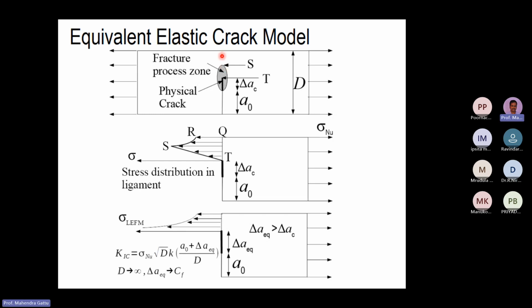Yeah. So if you see here, this region it is uncracked. Nothing has happened here, so the peak load has not yet been reached here. But at the crack tip, the peak load has been reached, the material has broken down, and then the load carrying capacity has reduced. So actual load carrying capacity is this much only in this region. If you are near the crack, it is very less.